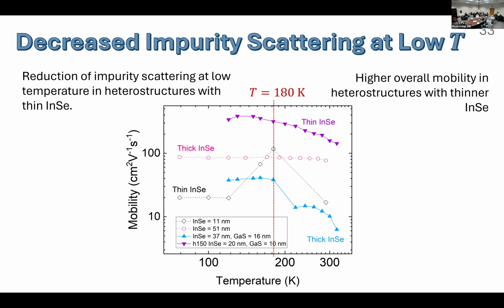However, in our heterostructures, we see that it's similar to what we would see for thick indium selenide. So essentially, we are able to decrease the impurity scattering in the heterostructures with indium selenide by introducing the gallium sulfide to the system.